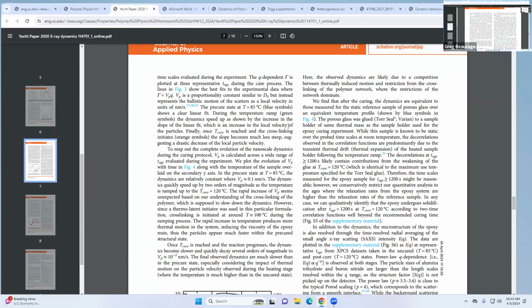A lot. In light scattering, you're shooting a laser at your sample, right? That's got some energy to it. X-rays are orders of magnitude higher energy. One thing we face a lot, especially in polymers and soft materials, is beam damage. You're shooting this X-ray, really bright, with a lot of photons. You can literally fry through material and degrade it in real time.